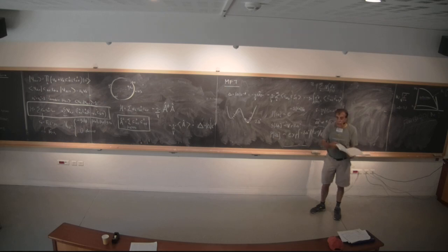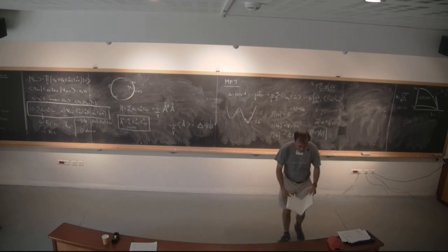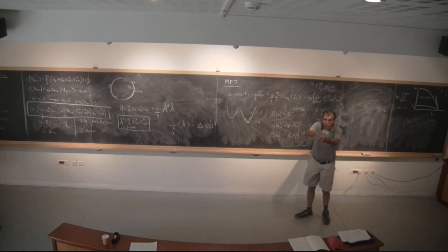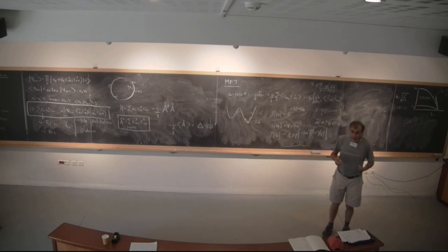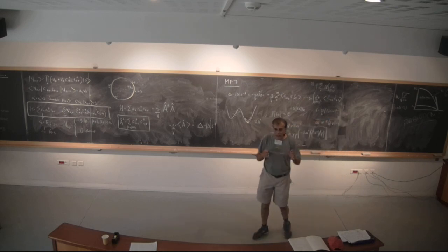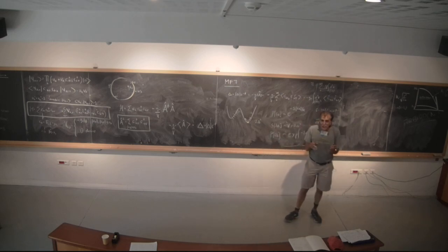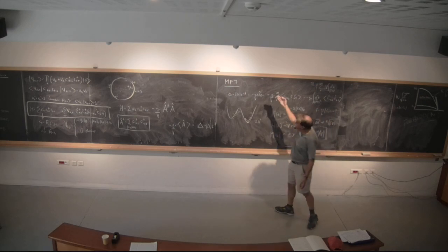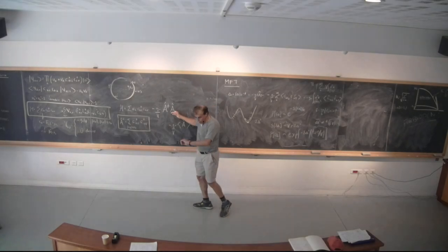Now, in a real superconductor, you're dealing with a sum over particles within the coherence length, which is very, very large, and so the fluctuations are still quite small. If you go to a strongly interacting superconductor with a small coherence length, the things I'm saying here become completely inaccurate. But in this particular model, the fluctuations in A are of order the volume.